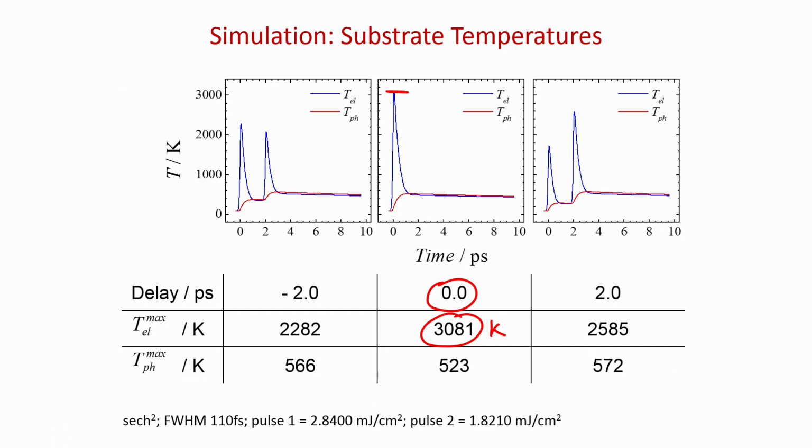When I increase the temperature, electron temperature and phonon temperature both increase simultaneously, in equilibrium with each other. But when you deposit heat energy to the surface, then for the first 1 picosecond time scale, they are in a non-equilibrium state. They are not in equilibrium. Why?